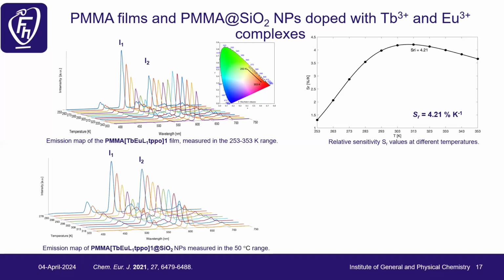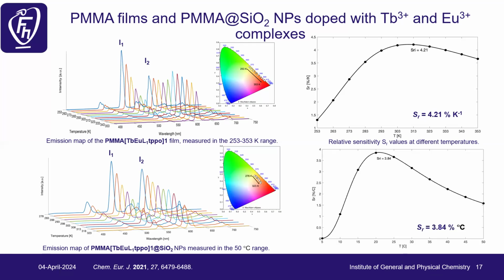Then I put it in silica and we got almost similar change of color, quite similar. So we were putting the same terbium europium. We were coating in this case the polymer silica coating on top of silica nanoparticles. We were putting a coating of PMMA and got 3.8% at 20 degrees. So it's quite good for the purpose that we want if we want to use it in cells or something like that.